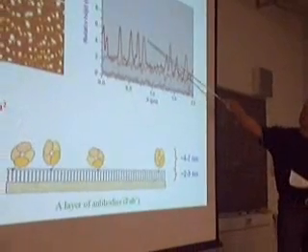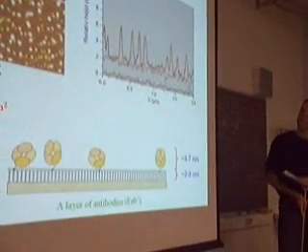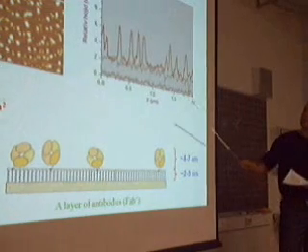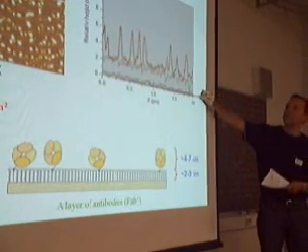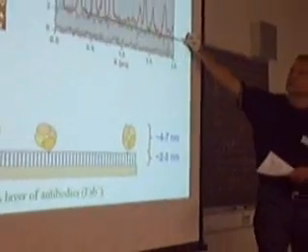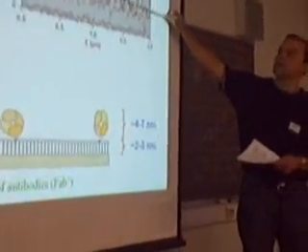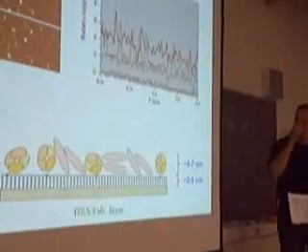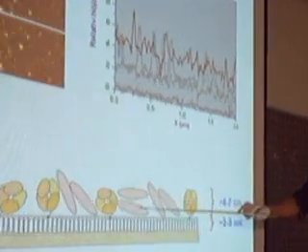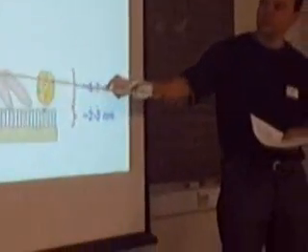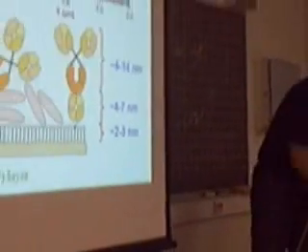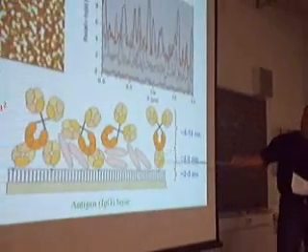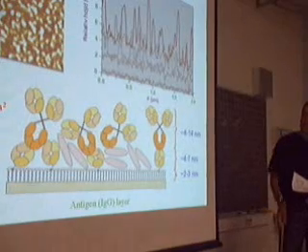And we can again read out their dimensions, especially height, from the height profiles here. That's possible because we have a very, very flat substrate as a reference, and also the lipid monolayer is flat enough, which gives the possibility to read out where you have the proteins there. Obviously, we don't want the IgG to be immobilized on these empty spaces here. So we have to block these out, and then we use, for example, BSA to block these empty spaces. So that eventually the IgG comes and reacts only with these ones. And this is the very specific reaction that we are looking for.